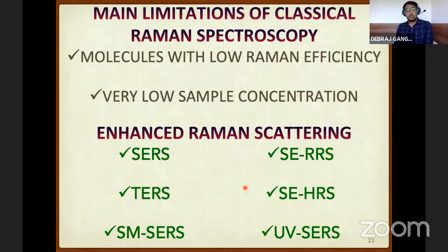Now, classical Raman spectroscopy has some limitations. The main limitations of classical Raman spectroscopy are that it's not capable of studying molecules that have low Raman efficiency, and it's not very suitable when the sample concentration is very low. So to overcome these two main limitations, different techniques have been developed to enhance the Raman signal, like surface enhanced Raman scattering, surface enhanced resonance Raman scattering, tip enhanced Raman scattering, and many other techniques, out of which I will be talking about surface enhanced Raman scattering now.